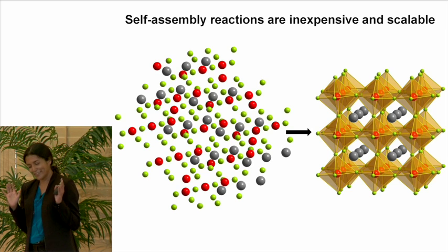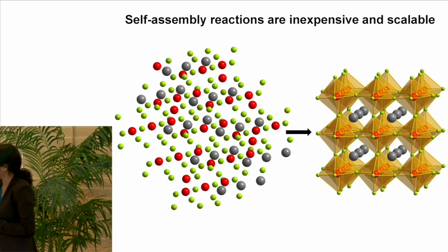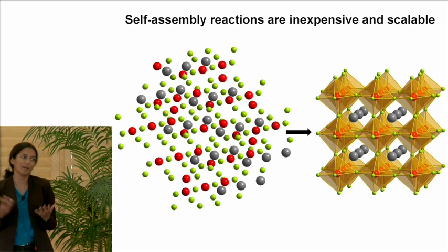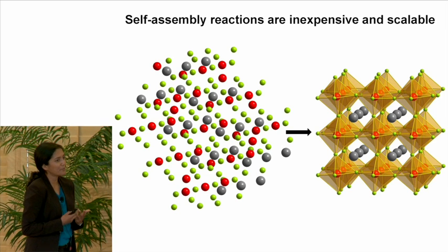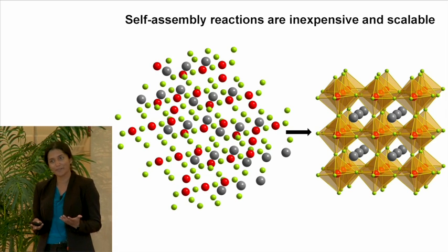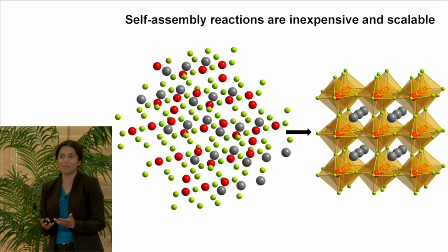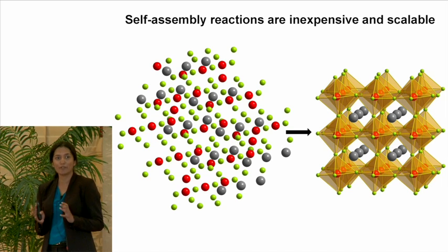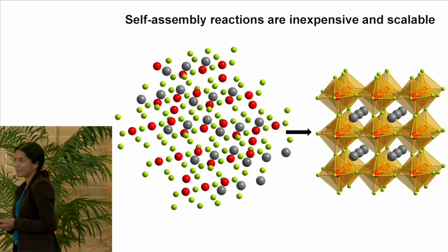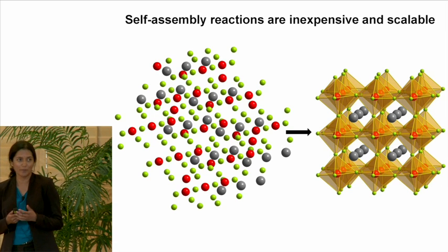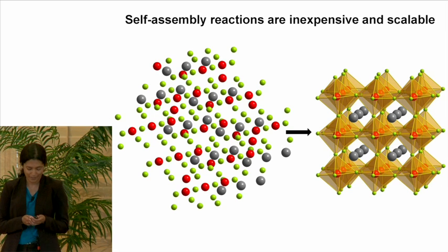When you get the conditions just right, you can isolate these hybrid perovskites as crystalline powders, thin films, and in my group, we love to grow single crystals because they are beautiful, and also because you can do very precise measurements on well-formed single-phase single crystals. In fact, every picture I show you is from a single crystal X-ray diffraction study.